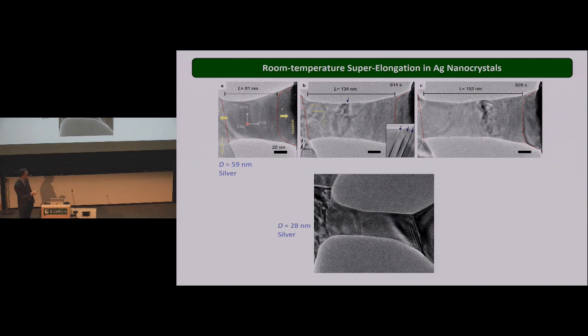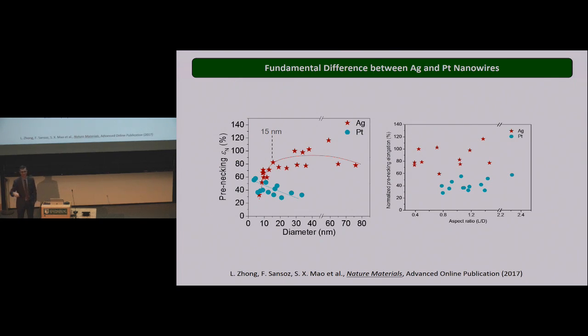Right? Never breaks. Now, when you look carefully, crystal slip is still present in this wire. So it's not like the liquid-like behavior. There is crystal slip in there, but also we have high plasticity. So the students repeated this many times, and we see clearly that silver is much more superplastic in this range of diameters than platinum. This represents the ductility before we observe a neck in the wires. And we achieve values over 100%, okay? And this is very clear that silver is a much better material to resist the strain in this application.